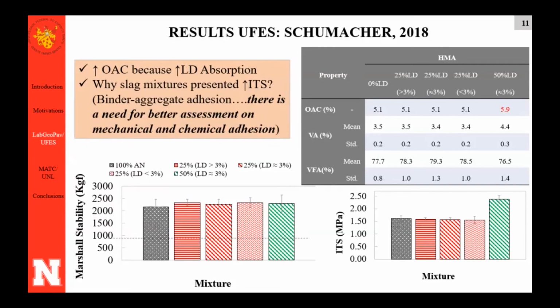But even at 5.9, there was no problem. It's not that much, let's say. It's still economically feasible. It's not a number like 8% binder. In terms of mechanical performance, as I increased the slag, nothing happened with the Marshall stability. We still got the same results. And even with 50%, I still have the same Marshall stability. It didn't decrease, but it didn't increase either.